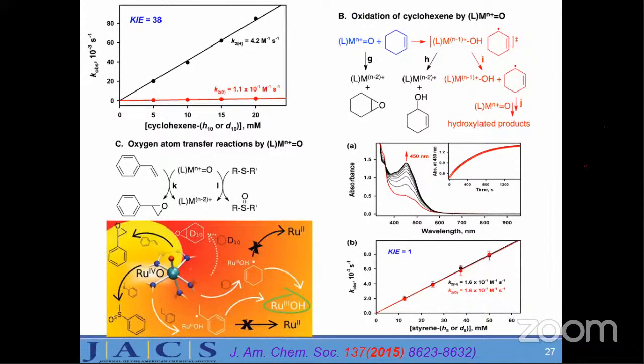Then, like in my manganese compound, we thought we would do it with cyclohexene. So we thought of doing it with cyclohexene. When we did cyclohexene, interestingly, you will notice that we again got a different KIE. It is not a KIE equal to 1, but we got a KIE more than what is shown here. So based on this KIE, one can straightforwardly say that epoxidation is not taking place here, right?